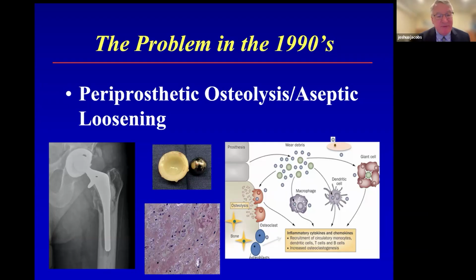They didn't have an infection, but they would come back, and you can see in that lower left x-ray a fair amount of bone loss on the femoral and acetabular side, showed as radiolucencies where there should normally be bone. And this was driven, we thought at the time, by debris generated by the bearing surfaces, where the femoral head would rub on the acetabulum. And the upper center is the metal on polyethylene bearing surface at the time. It's a cobalt chrome molybdenum alloy, and at that time, an ultra high molecular weight polyethylene component.